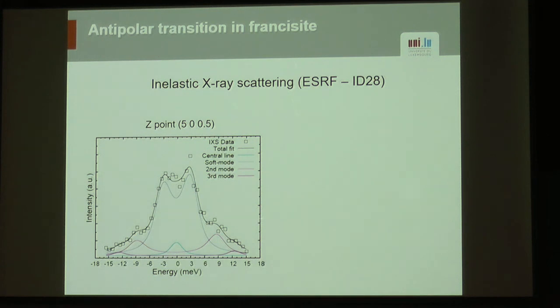And this is what the spectrum then looks like. This is at the ESRF, ID28. At this Z point where we expect the instability, we do find a mode that is soft. There are also other modes up there, which is not a surprise, given the complexity of the structure and the phonon modes from the phonon calculations that I've shown you earlier. But essentially, this mode is here.